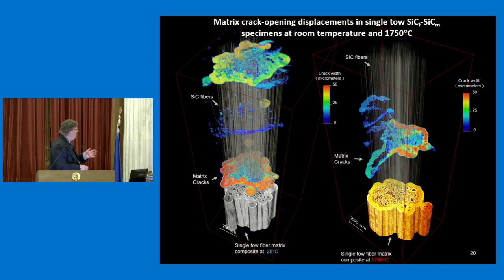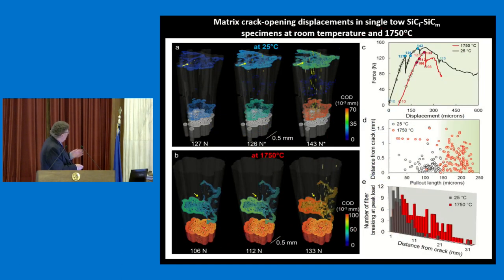So this is a very, very powerful way of getting information of a damage mechanism or resistance to damage at temperature under those conditions. So this has been extremely useful for trying to predict how long these materials will last under given situations. We can get all the data, everything you can see on these pictures, we can basically know exactly what the numbers, where it is, size, movement, and everything.